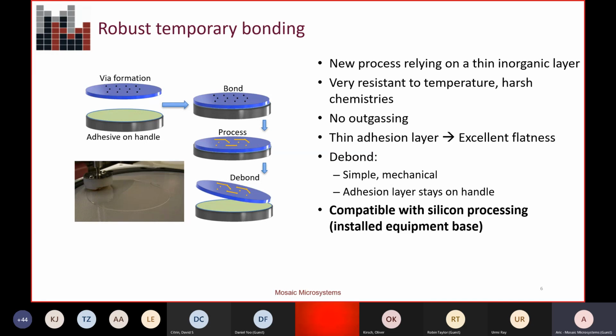The other important thing is it's very thin. It's not a 25 or 50 micron thick organic adhesive. It's a very thin submicron layer. That's important for a couple of reasons. One, it allows you to maintain good flatness and planarity for your lithography steps, for example, and gives you the opportunity to go to finer line and spacing.